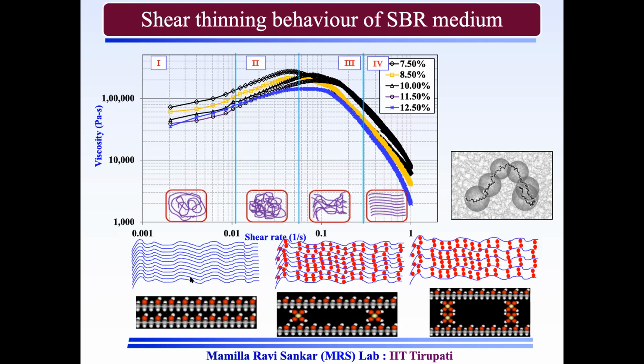In normal cases, polymer chains will have dominating elastic characteristics. By incorporating plasticizer, I can manipulate or imbibe the viscous characteristics. Now, how much viscous characteristics I want to imbibe will be known from some of the other rheological characterizations. But from this particular curve, as you increase the low molecular weight polymers or the plasticizer, which are nothing but the oils, the distance between polymer molecular chains increases, and the interpolymer molecular force of attraction will decrease. That means that you are imbibing the viscous nature to a dominating elastic characteristics polymer.